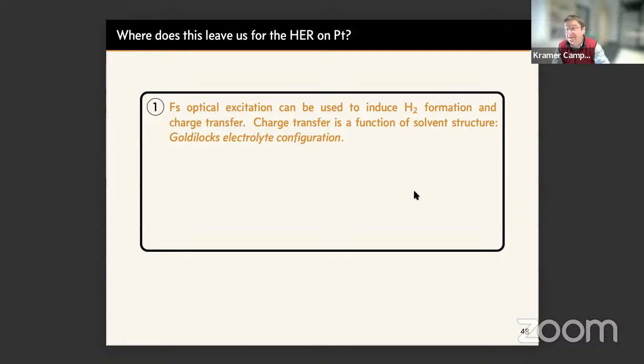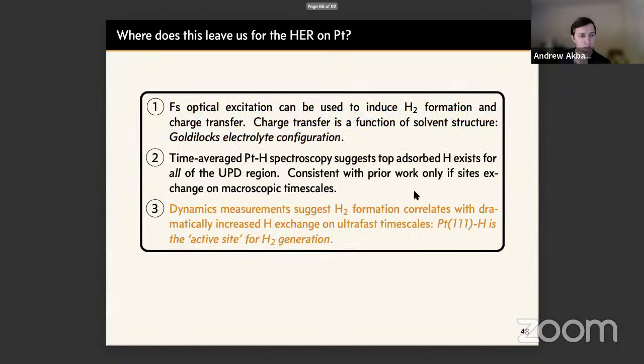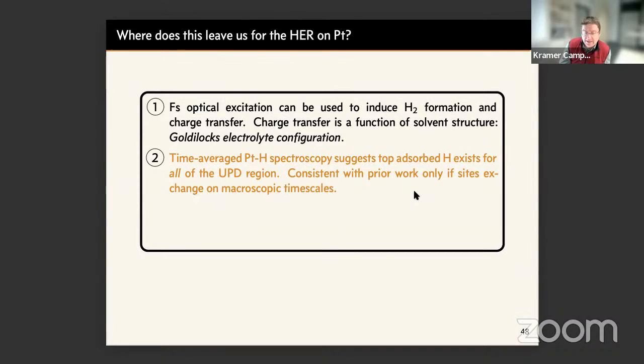So where does this leave us for hydrogen evolution on platinum? Well, I want to contend that I've shown you that femtosecond optical excitation can be used to induce hydrogen formation, H2 formation, charge transfer. This is a function of solvent structure. And that time averaged spectroscopy suggests top adsorbed hydrogen exists for all of the UPD region.